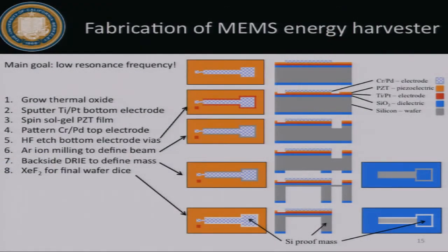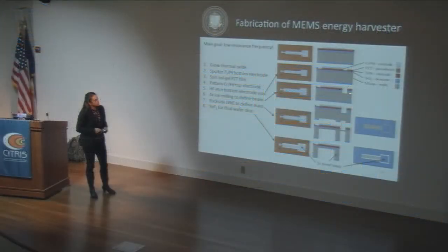So real quickly, the MEMS fabrication steps that I used to build the first device: I started with a blank silicon wafer, which is gray, grew a thermal oxide layer, which is the blue color, then sputtered a titanium platinum bottom electrode, which is red, and then sol-gel spin deposited the piezoelectric layer, which was PZT, lead zirconate titanate, the orange layer. Then the first masking step was patterning a chrome palladium top electrode, which is checkered here, and then etching with HF to reveal the bottom electrode, and then another etch using argon ion milling to reach down to the silicon layer, then backside etching to remove the oxide and silicon, and this big chunk becomes a mass at the tip of the beam. This becomes the beam. And then the final step was to etch away this little connecting silicon layer to leave a freestanding beam.